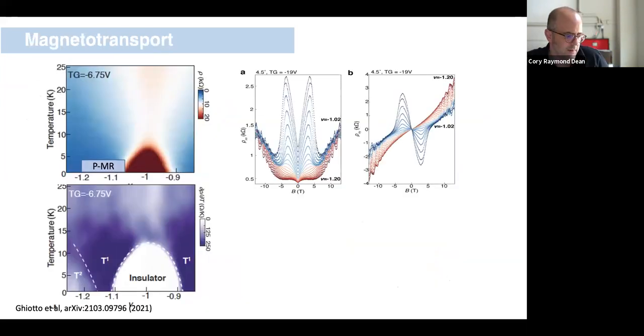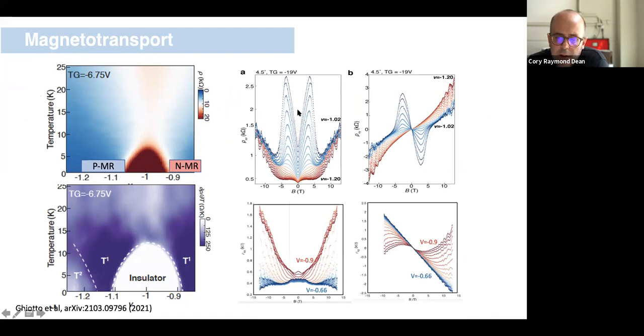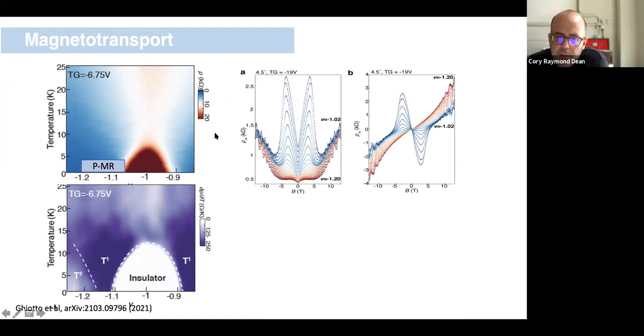Okay, so the last thing I want to touch on is that we measured the magnetoresistance around this metal insulator transition in some more detail. And this shows really exotic behavior. Here in the top left, sorry, I'm showing longitudinal resistance right near the quantum critical point on the overdoped side. Here on the left is longitudinal, and on the right is the Hall resistance. What we see is that the longitudinal is dramatically non-monotonic. It shows a strong positive magnetoresistance, then a peak, and then it somewhat recovers the positive magnetoresistance again.